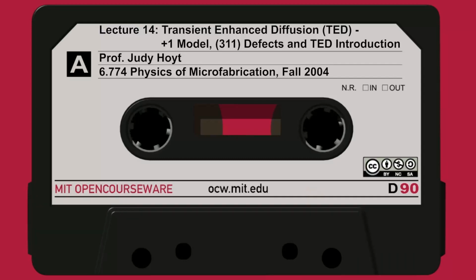Actually, if we want to be a little more sophisticated, people since that time have come up with what they call a plus n model, where n is of order 1, but not exactly equal to 1. And this is Pelaz et al. from the MRS meeting in 1997 came up with this sort of plus n model. What they were saying is that the multiplier on the original ion implant dose may not be exactly 1.